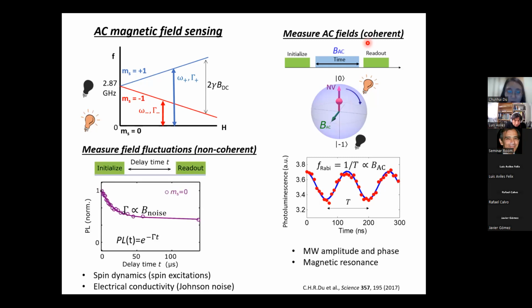In addition to coherent microwave field, we can also use the NV center to measure non-coherent microwave field, for instance, magnetic fluctuation, like magnetic noise. And this takes advantage of the NV relaxation rate experiment. So in this case, we can initialize the NV center at the 0 state, and then monitor how long it takes for the NV center to relax to the mixed state in a noise environment. So we will see that photoluminescence will follow the exponential decay as a function of the delay time, and the relaxation rate will be proportional to the noise at the NV location. So this allows us to measure the spin excitation, like spin dynamics, as well as the charge excitation, for instance, Johnson noise, to study the electrical conductivity of quantum material.